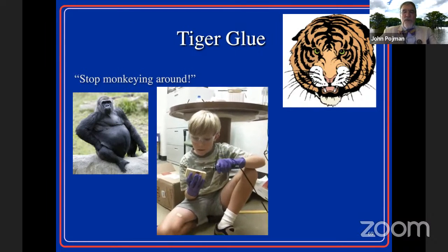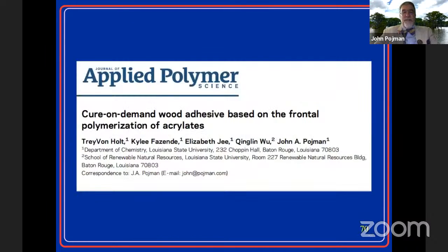So it does work. We were able to actually make a cure-on-demand wood adhesive. The problem is it doesn't work unless the layer has a minimum thickness of about 0.3 millimeters. So that kind of limits its application. It also has trouble working on systems that absorb heat well. For example, different types of wood have different thermal conductivities. And so that led us to say we need to get better chemistry, more reactive chemistry. That's what we're studying now.